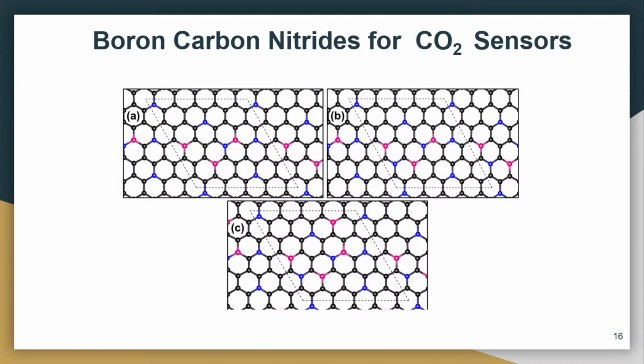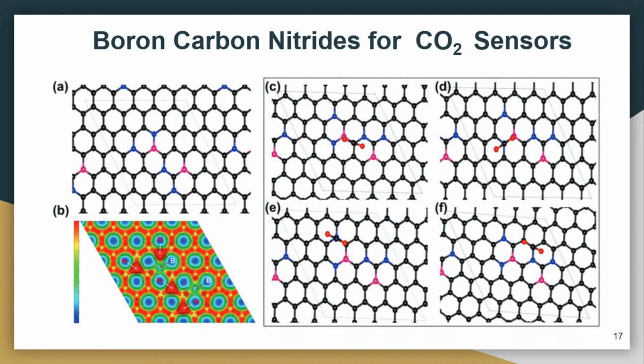Then we thought, okay, this will be considered as a nitrogen-based sensor. But unfortunately, when we did the experimental analysis, the experiment came out in such a way that this material has high sensing properties for CO2, right? Why? Because... yeah. So this is the ultimate. We did different ones, but finally we are taking this structure. Why? Because this is very close to our experimental findings, right? And this is the final structure for BCN, boron carbon nitride, for CO2 sensors.